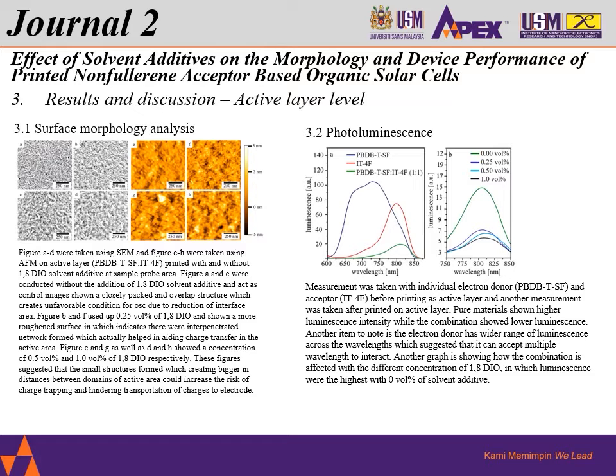Another item to note is that this donor has a wide range, it can cover a wider range of wavelengths, which suggests that it can accept multiple wavelengths to interact. Another graph shows how this combination is affected by different concentrations as mentioned earlier. With zero, if we're not adding DIO at all, it has very high luminescence as opposed to adding some of it, which is almost comparable.